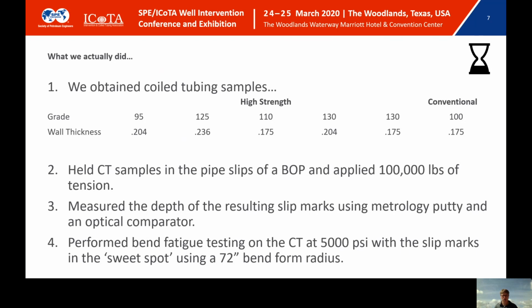The 95 grade coil and one of the samples, a 130 grade, are 204 wall. The 125 grade was 236 wall. The 110 was 175 wall. The other 130 grade was 175 wall, and the conventional was 175 wall. So you can see that we were at the mercy of our suppliers as to what they were able to provide in terms of samples in the tight time frame that we had. But we went ahead with what we had.